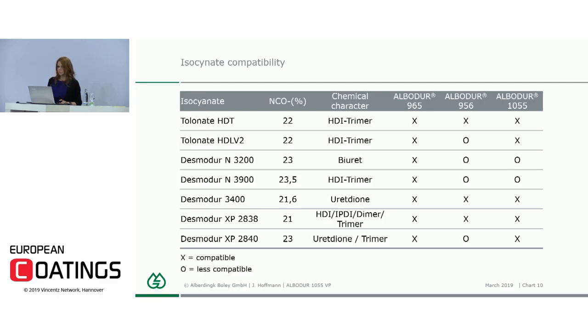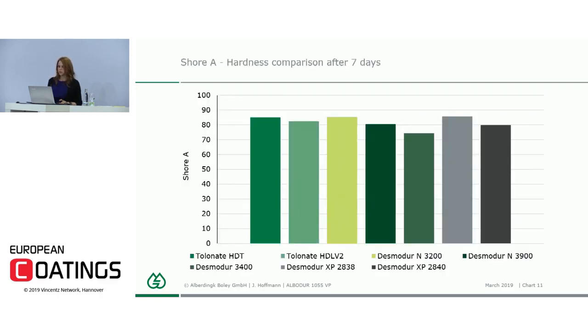So let's have a look at the impact of isocyanates. At first look, if we look at Shore A hardness after 7 days, we don't see a big difference no matter what kind of technology we are using. Doesn't matter if it is trimers or biurets, they're all relatively hard. The samples are also tested purely, so there are no fillers inside. Otherwise, there would be, I would say, around 10% harder than the results we have here. So what you can see is that by far the 2840, the 2838, is really hard, comparable to the 3200.